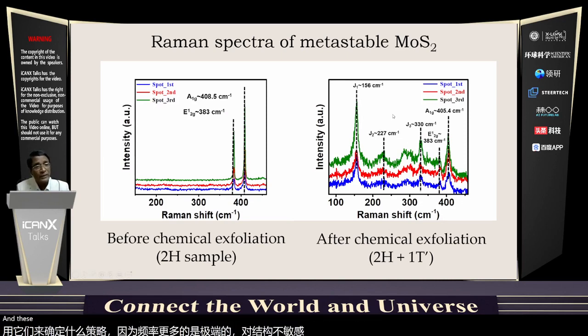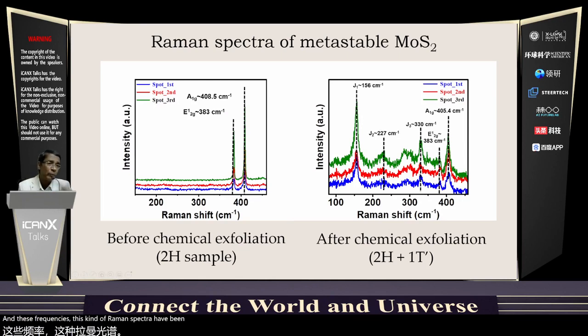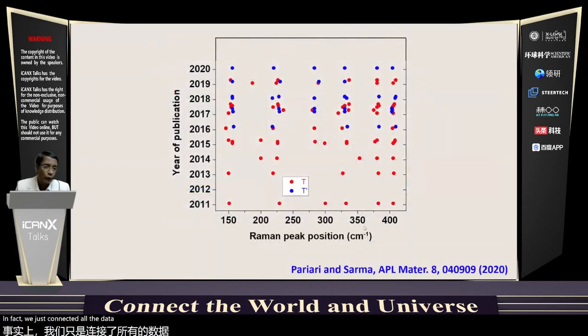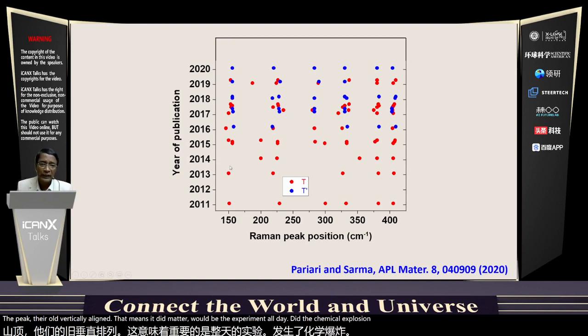And these kind of Raman spectra have been reported in the literature for the last decade. In fact, we just collected all the data and plotted them. What I'm showing you are Raman peak positions collected from various papers, and this compilation is published in this paper, in different years. And you can see that there's very strong consistency. The peaks are all vertically aligned. That means it didn't matter who did the experiment, how they did the chemical exfoliation, they always got the peak positions in Raman more or less at the same frequencies.